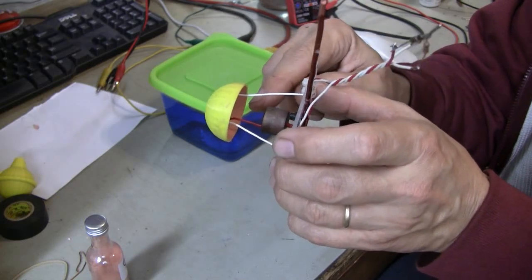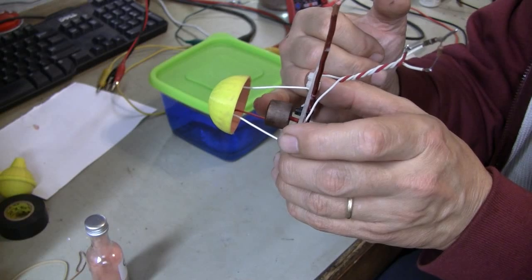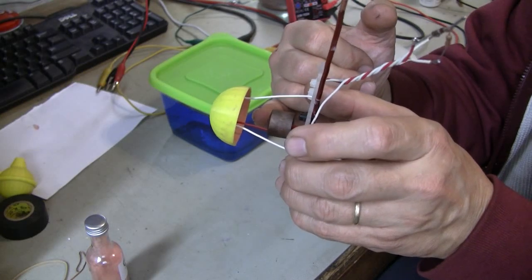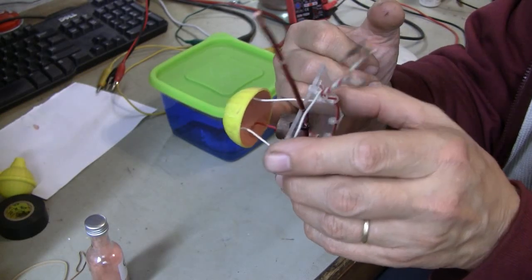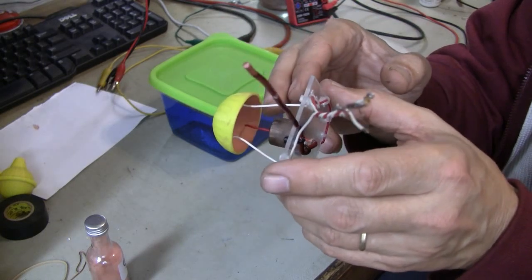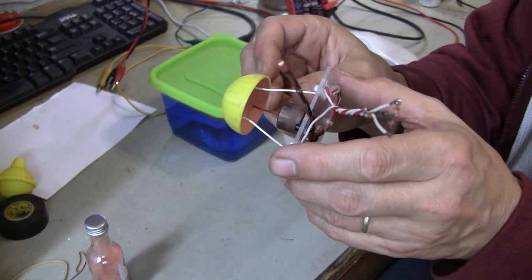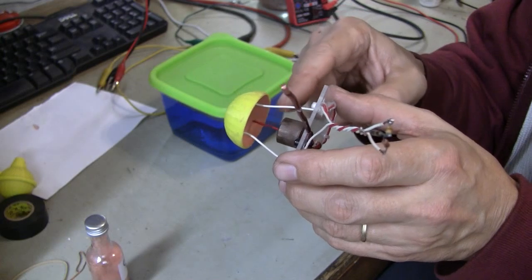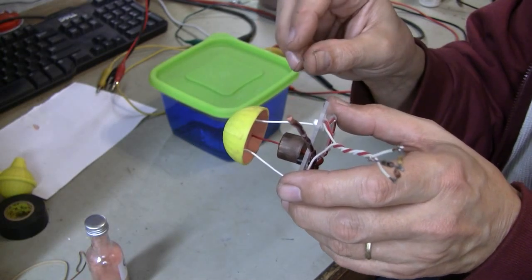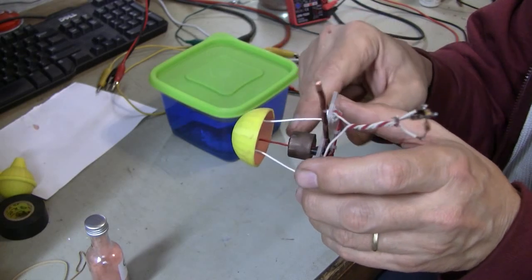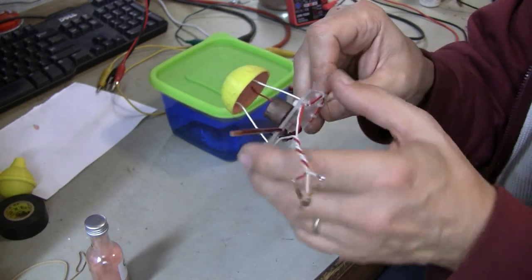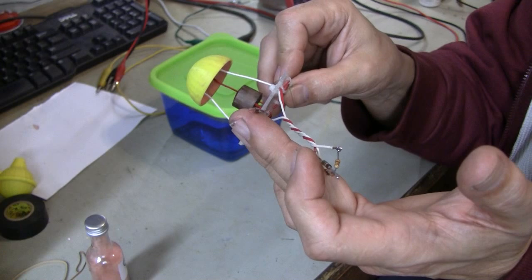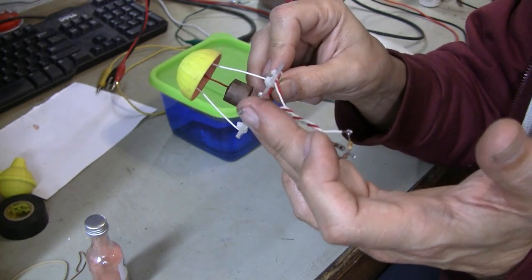And the amount of time that it takes for the copper plating to start spreading on the interior surface of the half sphere, as I stated earlier, is very rapid. So you can let it run for maybe an hour or even as short as a half an hour at only 2 milliamps per electrode. And then you can slowly ramp up the amount of current by increasing the voltage going to your input terminals here. So I'm going to start out at about maybe a volt, even less than a volt. And that will give me the 6 to 8 milliamps total that I want flowing into this circuit.